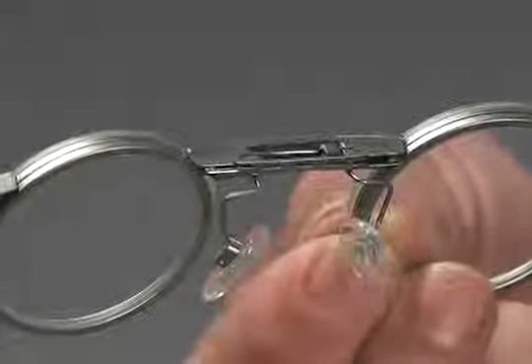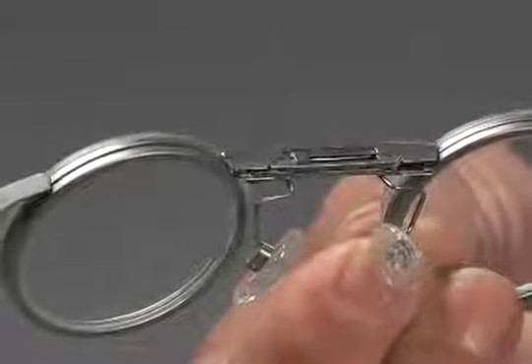The very thin walls and the subsequent susceptibility to thermal distortion presented a daunting challenge to the fabrication process, and manufacture by any means other than MIM would have been cost prohibitive. The parts are coined and then mechanically tumble polished to ensure a uniform surface finish. The successful execution of this difficult design breaks the current paradigm of process boundaries for MIM.